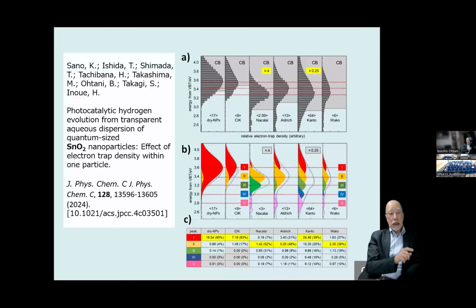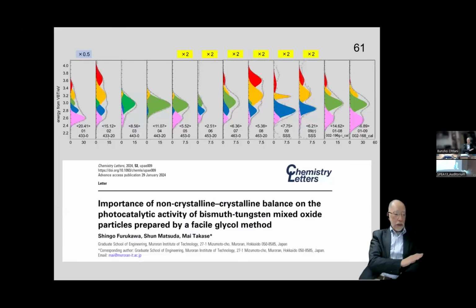And also in the tin oxide, SnO2, case, if the surface is almost completely covered with amorphous phase, that is highly active. And for the bismuth tungsten mixed oxide case, the sample is prepared to obtain a bismuth tungstate single phase. The inside, the bulk structure, is just a bismuth tungstate single phase. However, the surface is completely different depending on the preparation method and after-treatment. So that means the surface structure is completely changed, and this must give the photocatalytic activity.